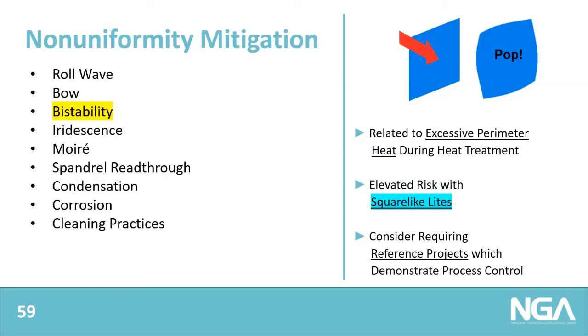The aspect ratio is the long side divided by the short side. As we get to a square panel, the aspect ratio approaches 1. So glazing panels of that nature have an elevated risk. Low aspect ratios correlate with an elevated risk of bistability. One way of navigating the issue would be to ask that the project team reference recent projects demonstrating process control in regard to square-like panels.